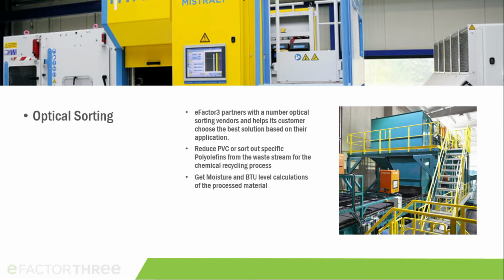In some cases, when we're talking about a mix of residual plastic from the MRF, we typically have 1 through 7 materials. And a lot of the pyrolysis plants do not like certain plastics. They like polyolefins, PEs, PPs, and in some cases PSs. PVC is something that always needs to be removed, and PET is typically also not desired. So we can integrate optical sortation in a system.